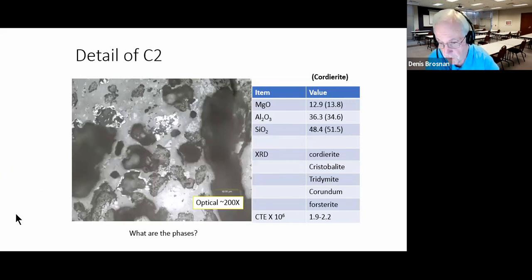Some detail of one of the groups, there's their composition here. In X-ray diffraction, we found cordierite, some cristobalite, which is not visible in the picture, or tridymite. Corundum is probably the lighter phase that's standing up here because of its hardness. In this polished section, we can see it. And cordierite and forsterite is down here in the background. The cordierite is probably the lighter gray phase, very typical of forsterite, magnesium silicate with cordierite in the continuum with some glass present, and pretty good thermal expansion coefficient. So in order to figure out these phases exactly, I would revert to scanning electron microscopy, but nevertheless, you can see the rounded pores here. Sometimes they're elongated in this microstructure.